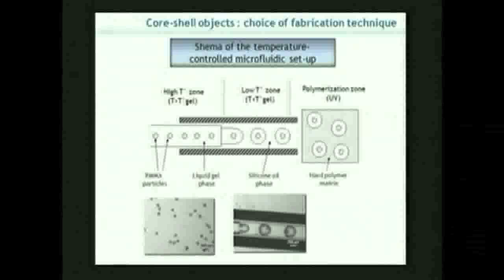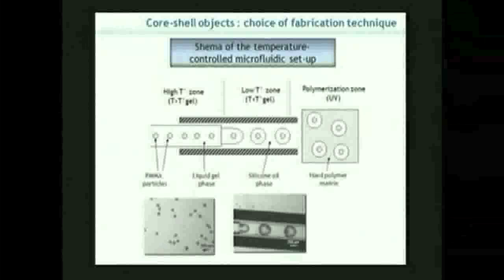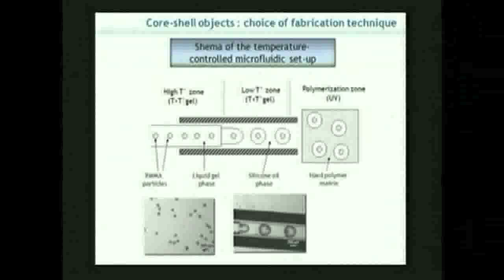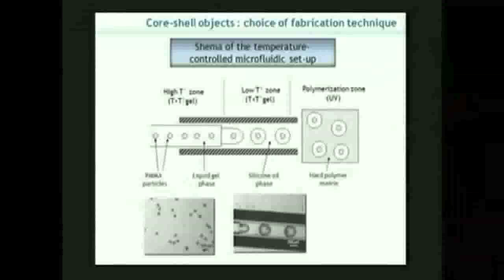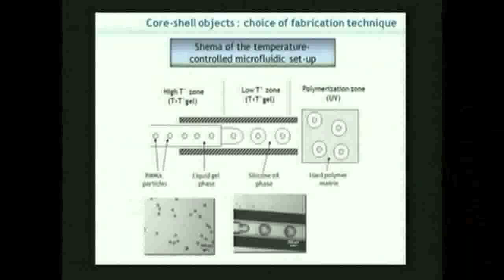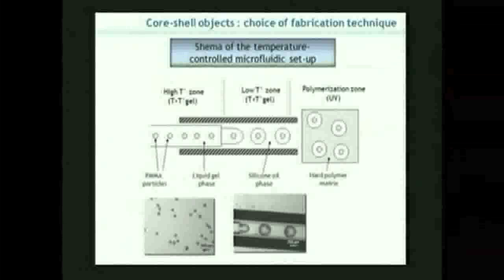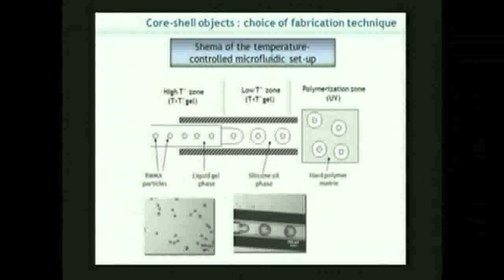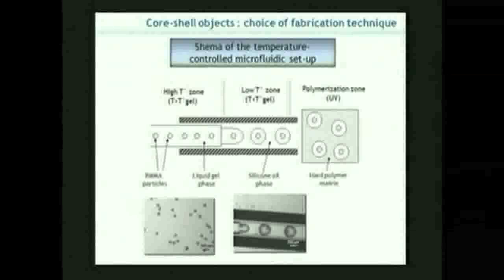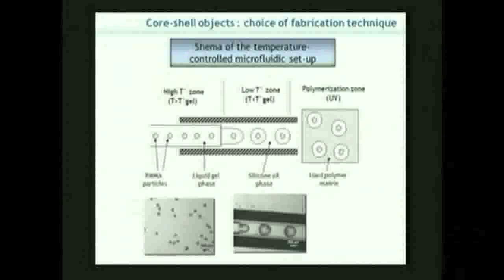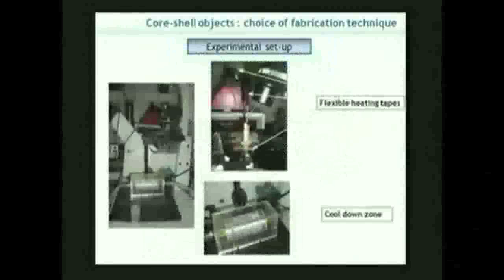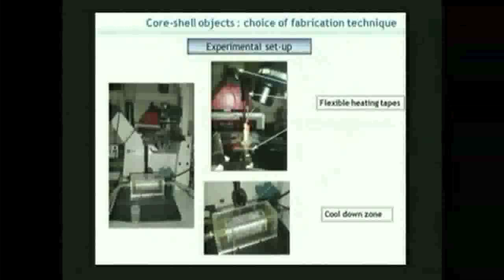Once we have encapsulated the particle inside this fluid phase, we decrease the temperature so that the shell becomes solid. Okay? And we end up with small particles of PMMA which are embedded into a gel phase, and these particles can be embedded into a polymer material that we can cure by a thermal or UV procedure or whatever. Okay, and this way we can make some objects with this type of property. Okay. So this here is the experimental setup that we've been using.